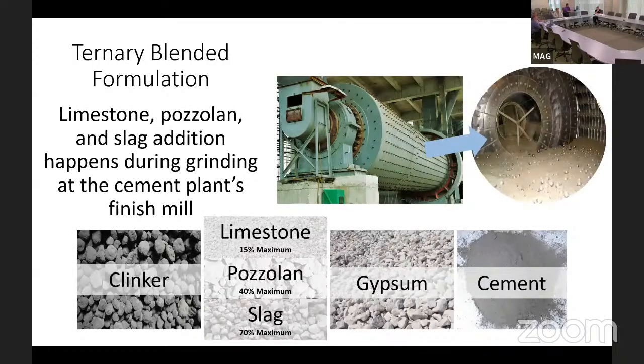Again, back to this slide here, same process, same materials, other than limestone. Now you're introducing either a pozzolan or a slag. Clinker is considered one of the products. So you've got clinker, limestone, and your third would be pozzolan or slag. Gypsum, again, is introduced to regulate set time, and you end up with an end product of cement that performs the same as ASTM C150 Type 2, 5, or the C595 IL.